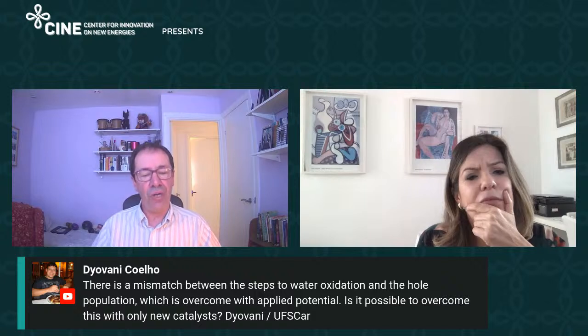And therefore, the interesting thing is that if you put a catalyst on the surface, the holes go to the catalyst, at least in principle. That separates the charge, but you don't have to lose kinetics, because you're still able to drive the catalysis because the catalyst can work at a smaller overpotential. I'm not sure it answers your question, but it's how I would think about it.